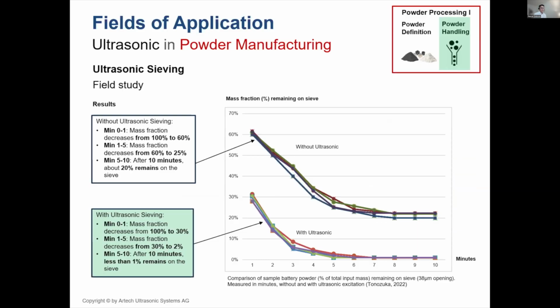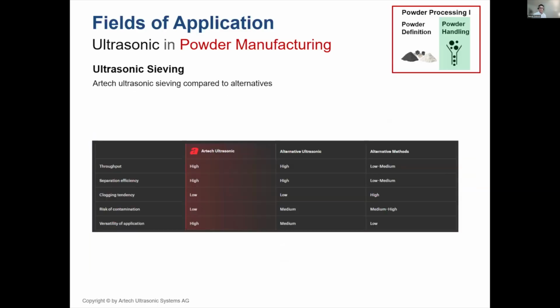After 5 minutes, about 25% of the powder was remaining on the sieve without ultrasonic, and with ultrasonic already only about 2% remained on the sieve. After 10 minutes, without ultrasonic, still about 20% was remaining on the sieve, whereas with ultrasonic, less than 1% remained on the sieve. So this clearly shows that the ultrasonic helps regardless of the powder, whether it's battery powder, metal powder, or polymers, to increase the throughput.